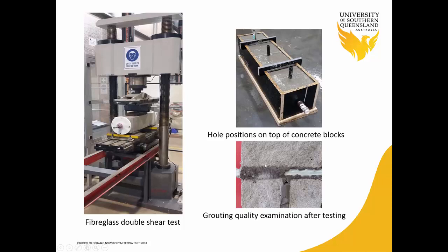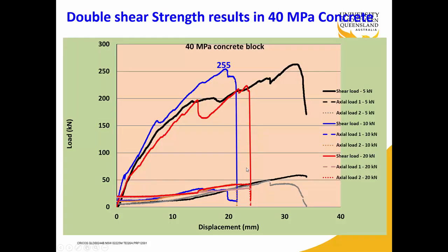After testing, the sample is dismantled and the quality of encapsulation is investigated. As you can see here, it was a perfect encapsulation, and we can observe that the imprint of rifling is captured in this test. Some of the tests are shown in the following slide. This shows a double shear test of fiberglass dowels in 40 megapascal concrete. The vertical axis shows the load in kilonewton, and the horizontal axis shows shear displacement in millimeter.